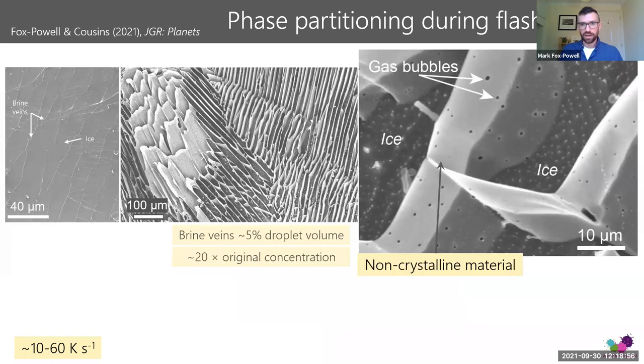So, a closer look at this brine vein material now, this light colored material. It's non-crystalline, this kind of glass-like material. It has these gas bubbles, these circular features, distributed evenly throughout it. This is good evidence that this has vitrified, has gone through a glass transition and has formed an amorphous phase.